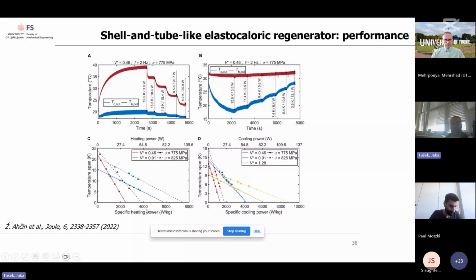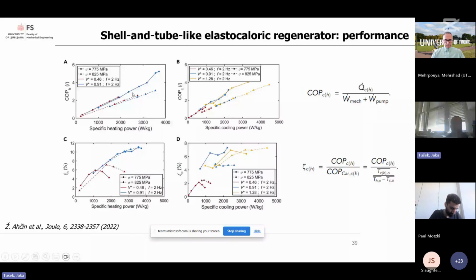We evaluated the system also from the efficiency point of view, so from the COP and the exergy efficiency, which is the ratio between the actual COP and Carnot COP, which is the theoretically maximum COP at which the cooling device could operate. We are not yet better than vapor compression, which normally operates with exergy efficiency up to 30%, but we are not that far considering that this is the new technology compared with the state-of-the-art technology.